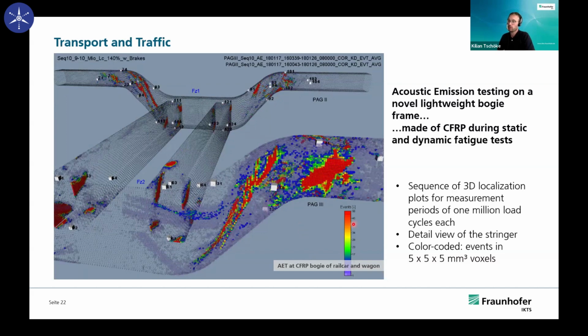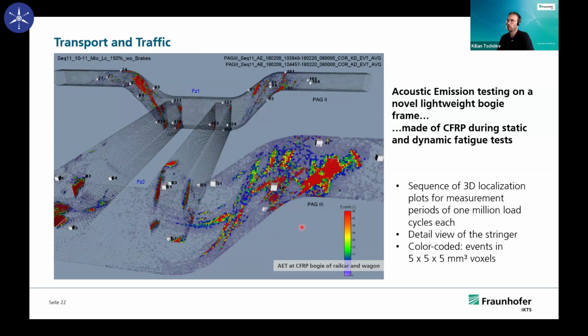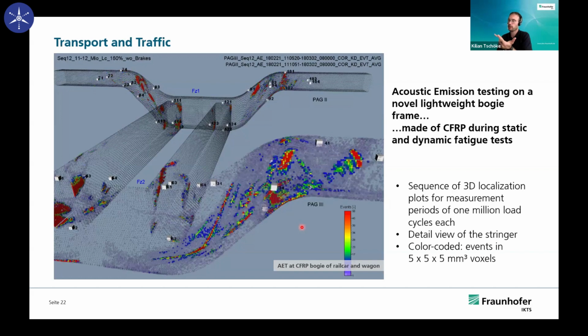You can also slightly assume even fiber bundles where a fiber breakage started. And you can also see areas where a delamination made a lot of noise. And this information you can later use to compare your design from the finite element model with the real life bending tests. And you can identify the weak spots in your structure.